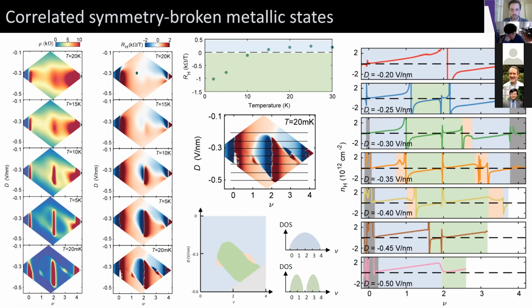Yeah, so that's a fantastic question, and I thank you for raising it. I should be more clear about this. Indeed, we expect the largest gap to be when the chemical potential is precisely at half filling, but this band is rather flat, and Coulomb interactions are large. We don't know the exact numbers of the bandwidth and the Coulomb energy scale, but we think the Coulomb energy scale is similar to or even larger than the bandwidth. So even when the chemical potential is detuned from half filling, Coulomb interactions are still large and can still drive some sort of spontaneously broken symmetries. And so the gap very likely doesn't close once you slightly detune from half filling.